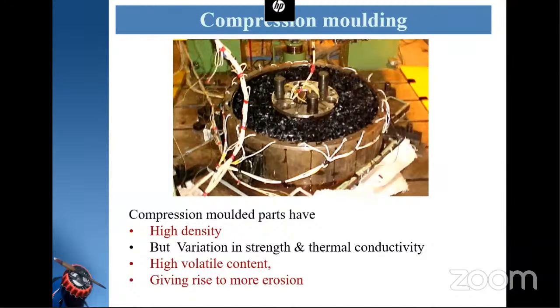Here the mold is filled with carbon phenolic prepreg flakes and it is put into the cavity of the mold. And the punch comes from the top and gets closed. Once it is heated and simultaneously the pressure is applied, we make the convergent of a flex nozzle system. Here we can get high density composites, but with variation in strength and thermal conductivity because of the flakes configuration, and high volatile content, giving rise to more erosion.